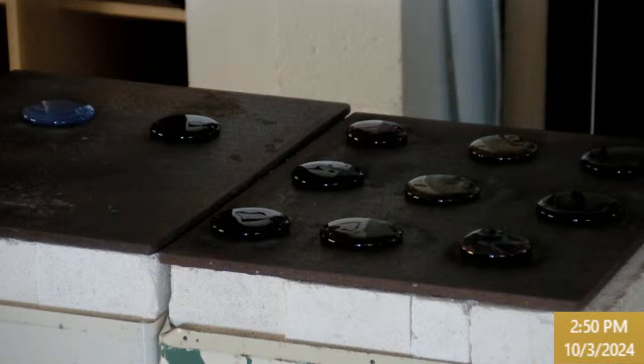A glob of molten glass goes into a preliminary mold. In a matter of seconds, it comes out as a miniature version of the bottle, known as a parison. Each parison then moves into a blow mold, the cavity of which is the shape of the final bottle. The equipment blows compressed air into the parison, stretching the glass outward towards the wall of the mold cavity. This process creates the final bottle shape and hollows out the inside. These are amber-coloured beer bottles. The colour is produced by adding small amounts of iron, sulphur and carbon to the glass mix.